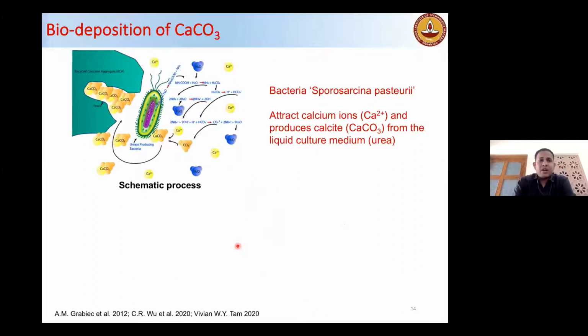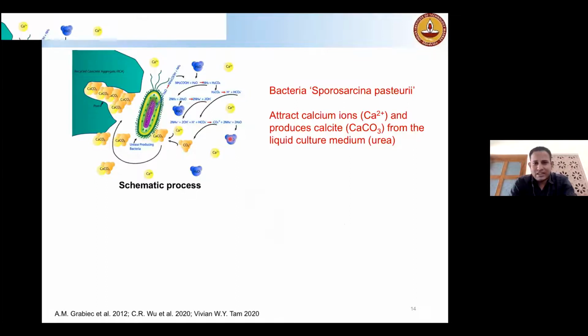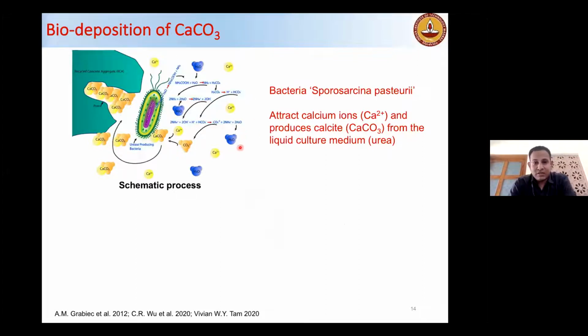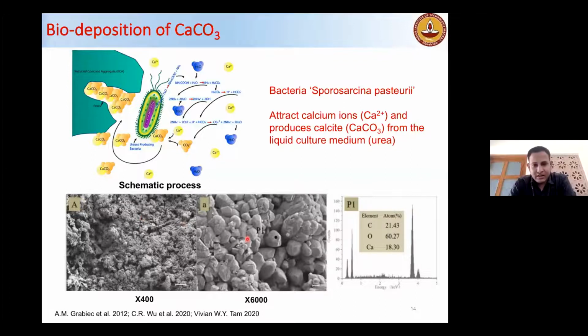So these are also filled with the pozzolanic materials. Next is the biodeposition of calcium carbonate. So using a bacteria, the pores and cracks of the recycled aggregate are filled. So this bacteria attracts calcium ion and produces calcite or calcium carbonate, which also requires a culture medium, which is basically urea. So in this process, the bacteria forms spherical depositions of calcium carbonate on the surface. So this will densify and improve the aggregate properties.